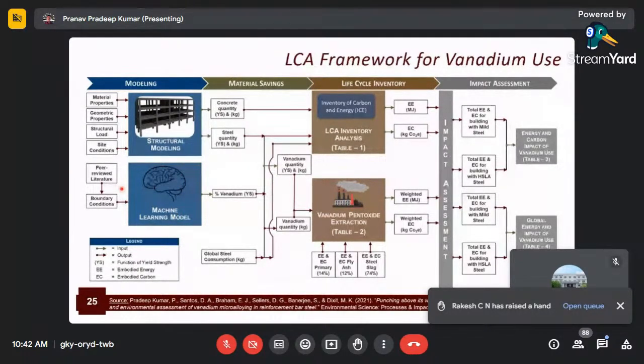For carbon and energy analysis, we use the inventory of carbon and energy for concrete and steel. And for vanadium, we use some literature studies to get that data. You can see here that the vanadium product is primarily obtained in a secondary form. Therefore, the footprints in terms of carbon and energy are very low for this particular commodity. Only 14% of vanadium is obtained from primary production. So finally, once we have the life cycle inventory, we combine all this to perform an impact assessment to compute the total embodied energy and embodied carbon of using mild steel versus the vanadium high-strength low-alloy steel.